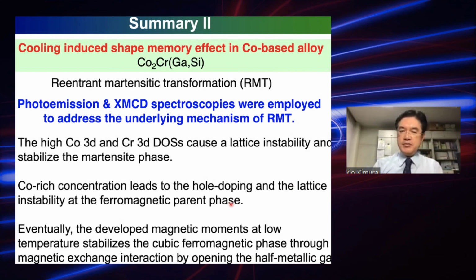So finally, we discussed the competition between the band Jahn-Teller effect and the half-metallic band structure. Probably the magnetic moment developed at low temperature maybe stabilizes the cubic ferromagnetic phase through magnetic exchange interaction by opening the half-metallic gap.